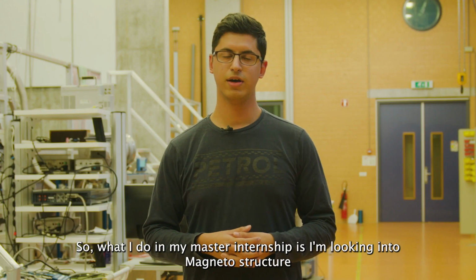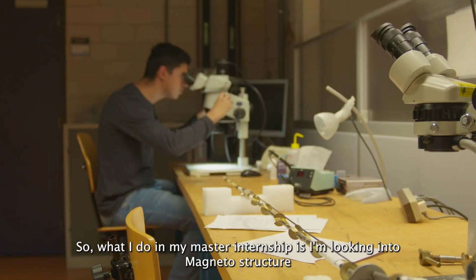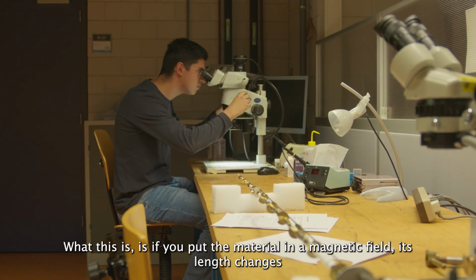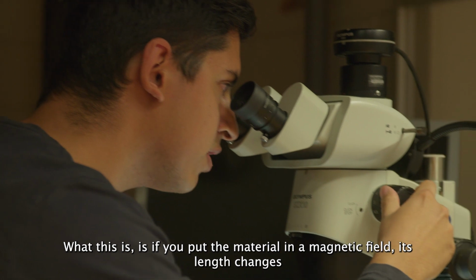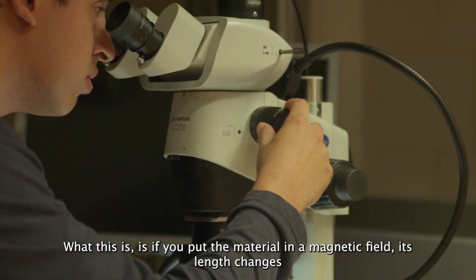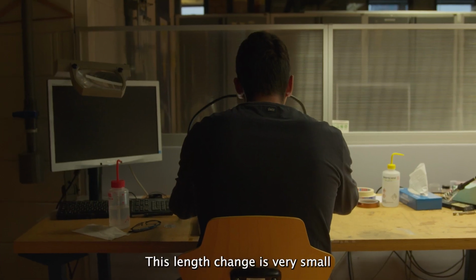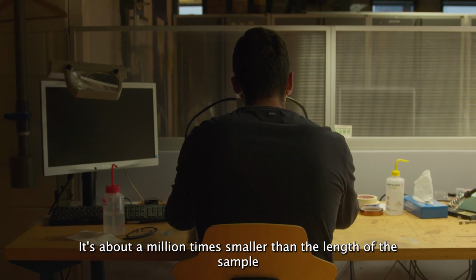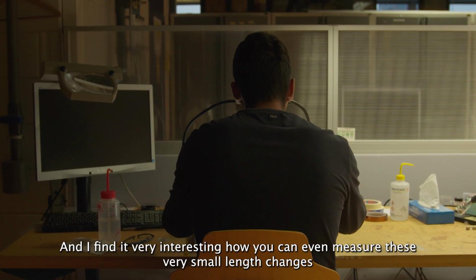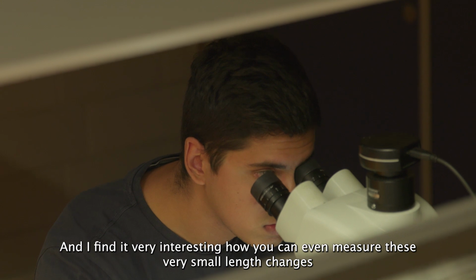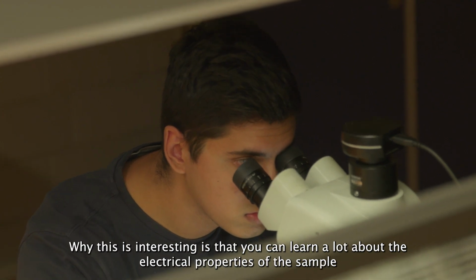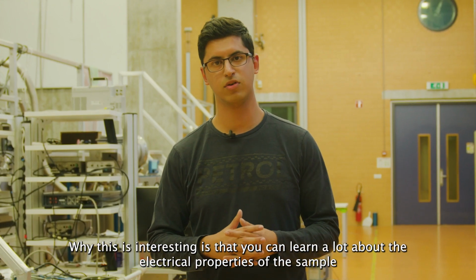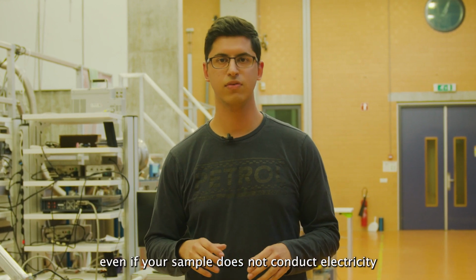So, what I do in my master internship is I'm looking into magnetostriction. What this is: if you put a material in a magnetic field, its length changes. This length change is very small. It's about 1,000,000 times smaller than the length of the sample. And I find it very interesting how you can even measure these very small length changes. Why this is interesting is that you can learn a lot about the electrical properties of the sample, even if your sample does not conduct electricity.